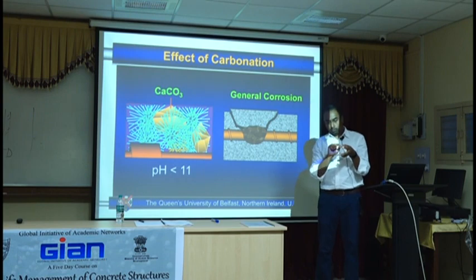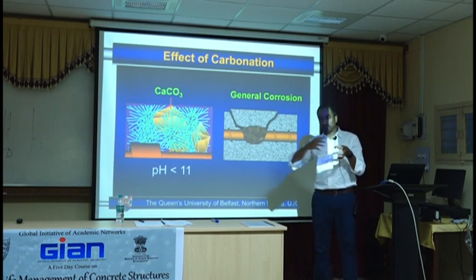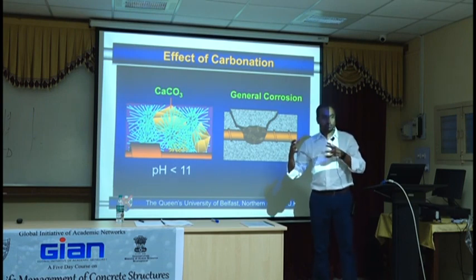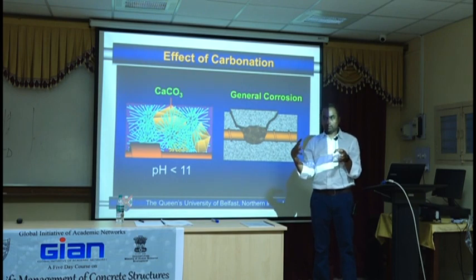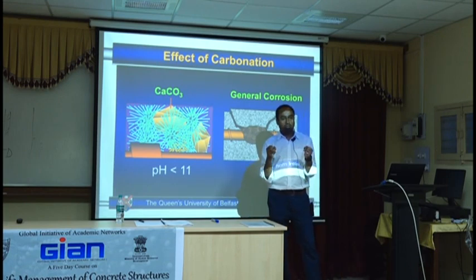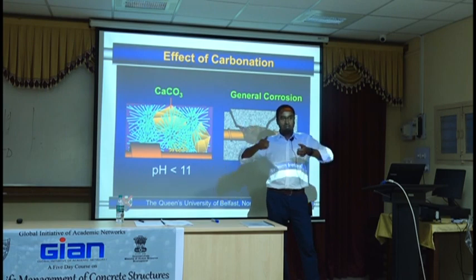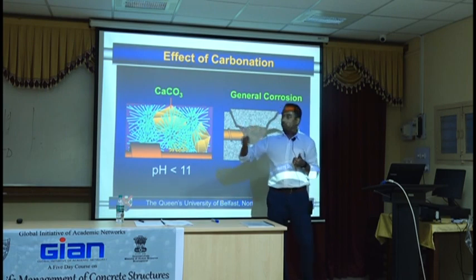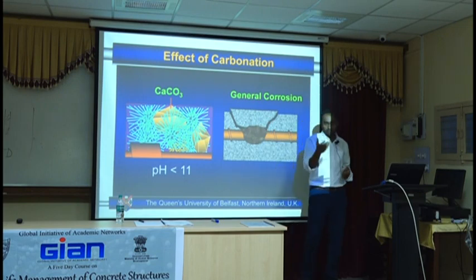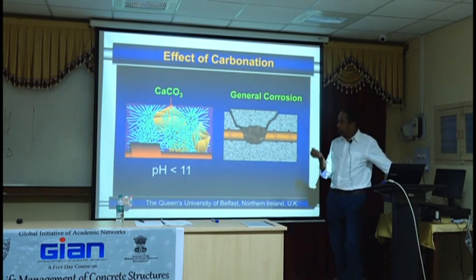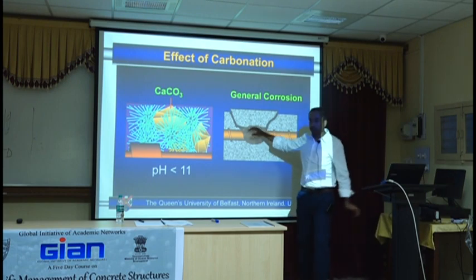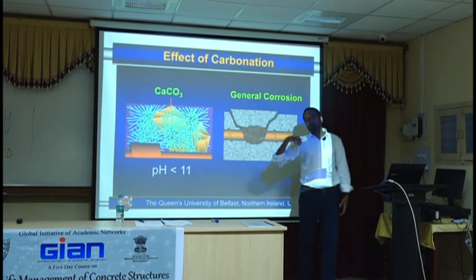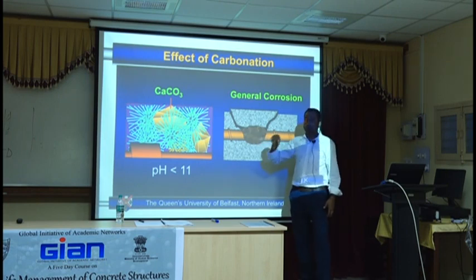But that's okay. It put a crack to the next pore and it connected that, and then it released that expansion force. Good. But then you have calcium carbonate forming in the next one, and it has nowhere else to go. So it then will have to go outwards. So all these micro cracks that you see in concrete eventually might lead to a macro crack. We call it spalling, whether it's popping or spalling. So when you get spalling, that means that steel is now exposed to the external environment. By then the damage is already done anyway.